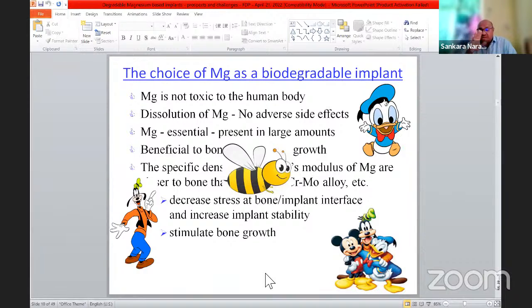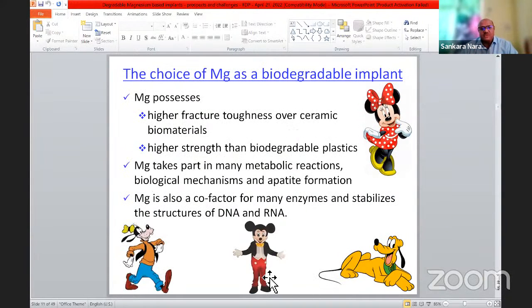Okay, so there won't be any adverse side effects. So that is the main advantage. Okay, and it is beneficial to bone growth, and the specific density and modulus of magnesium are much closer to the bone when compared to titanium or chromium, cobalt, molybdenum, etc. And because of that, it decreases the stress at the implant interface and increases stability of the material, and it can stimulate the bone growth by dissolving through the media and all those things.